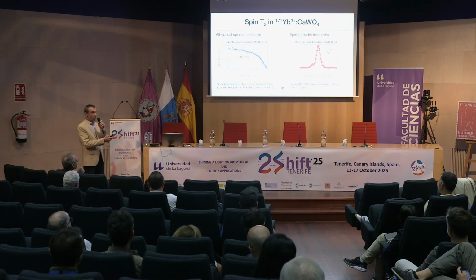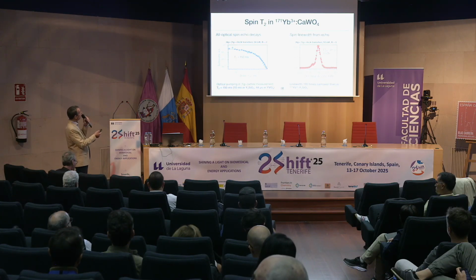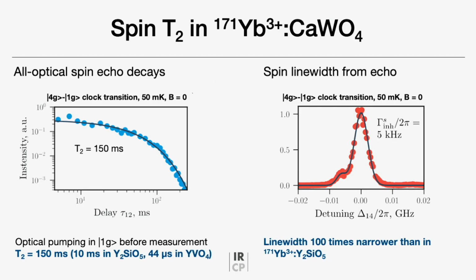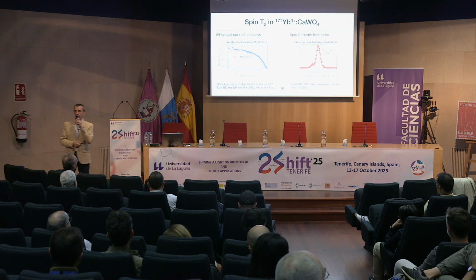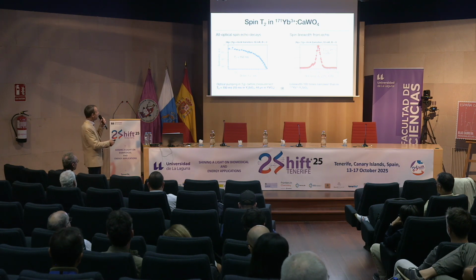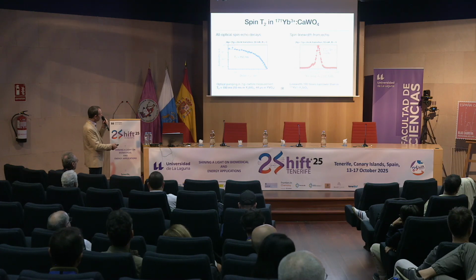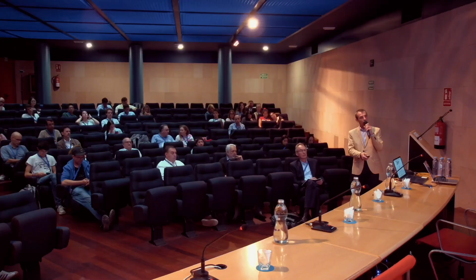Okay, next, of course, we also wanted to see how the spin transitions were behaving. So with the same technique, we were also able to look at the spin echo decays to determine the spin quantum state lifetime. We can do that with all-optical methods, because with the optical transition, we can drive the spin transitions. And here also we find a really nice result. If we look at this particular transition, which is insensitive to magnetic noise, again at very low temperature, we find a spin quantum state lifetime of 150 milliseconds. This was obtained by freezing the spin in a particular level, after optical pumping.